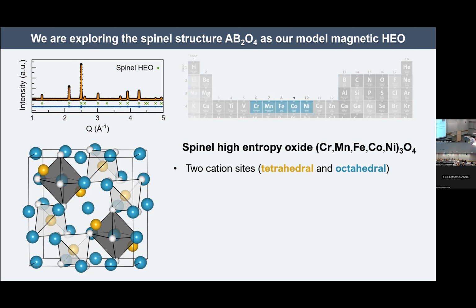A second feature that excited us about this structure in the context of high entropy is that in addition to the many elements that can sit on a spinel structure, we also have 2 nominal cation valences, 2+ and 3+. In a normal spinel, the 2+ sits on the tetrahedral and the 3+ sits on the octahedral, but they can in many cases invert. And we saw that immediately as a source of additional entropy, potentially.